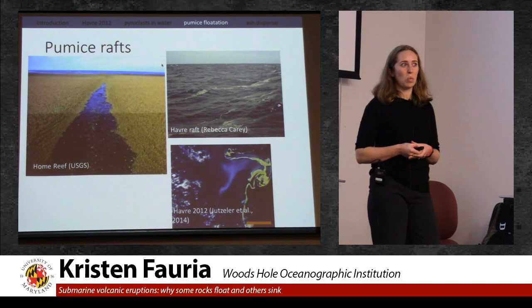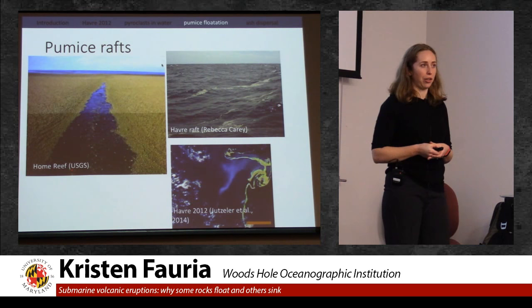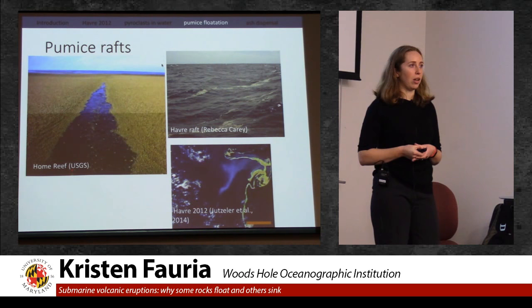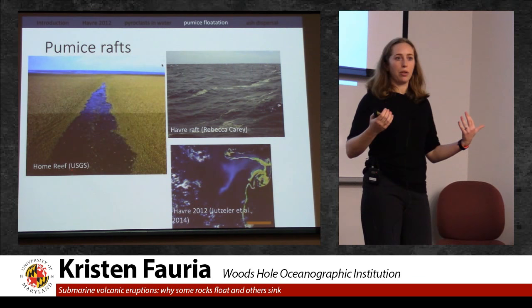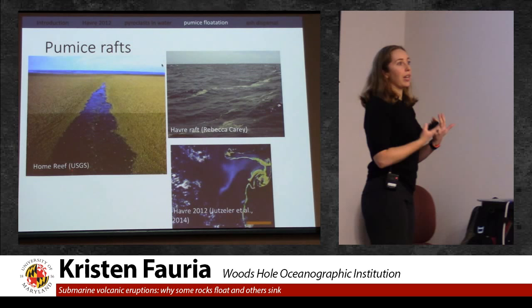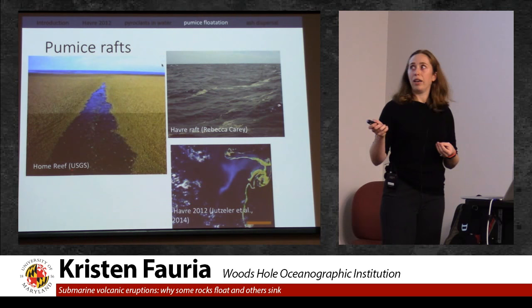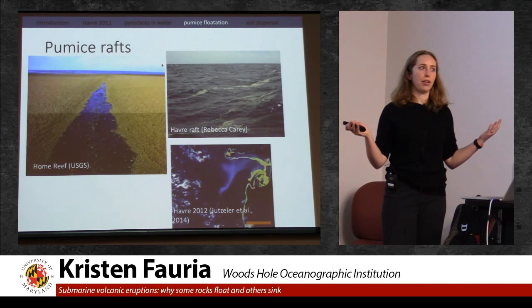Great question. We don't know what the initial size distribution of the raft was because no one was there to originally see it. The first observers got to the raft about a month after the eruption, and pumice in a raft is experiencing wave action, and they're abrasive, so they're grinding up against each other and potentially breaking down. We don't know exactly how quickly they break down, but potentially quickly enough that you see much smaller pieces later on. There was at least half-meter sized pumice, though, 1 month after the eruption.